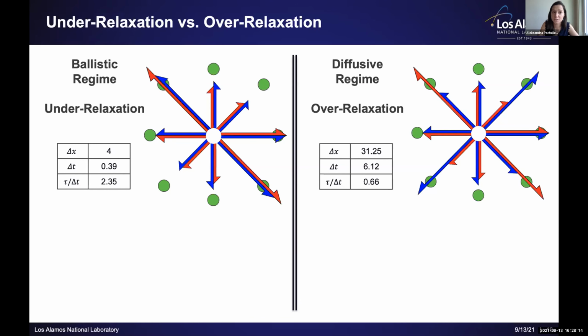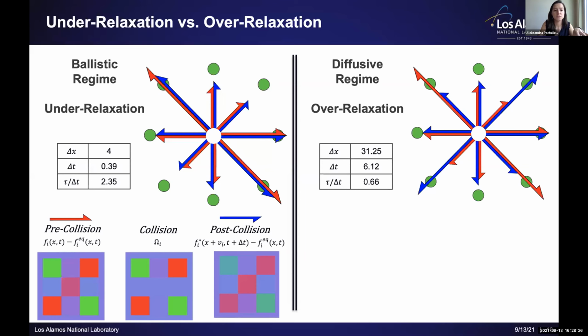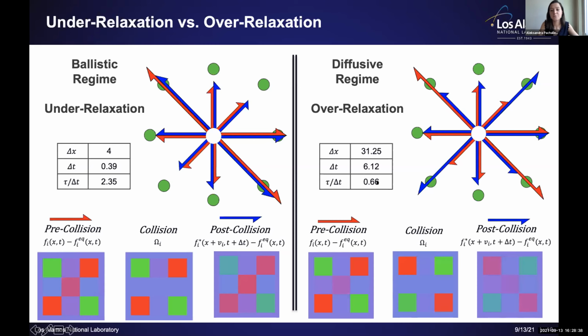Okay, how do we understand under relaxation and over relaxation? Here we see that in the ballistic regime, we always have under relaxation, and the pre and post collision terms have the same sign, going towards equilibrium or passing equilibrium. Whereas in the diffusive regime, we have different signs of the pre and post collision terms, as you can see here in red and blue, where the pre-collision is going towards equilibrium and the post-collision is passing through equilibrium. That's how we achieve over-relaxation, this zigzag effect seen before.